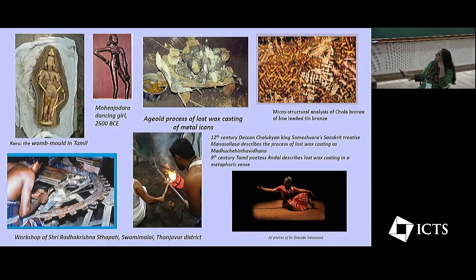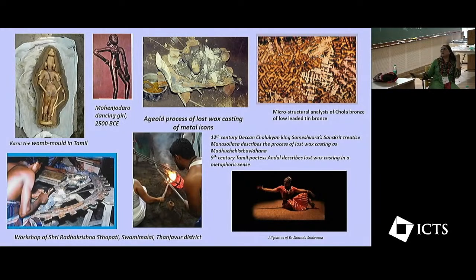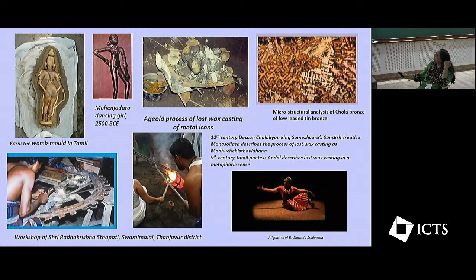And typically in the lost wax casting, what is done is first a wax model is carved of the icon to be made. And here you see from the rear this wax model having been carved. And then it is invested with numerous layers of clay, going from the finest grade of clay to the coarsest layer of clay. And here, what is important is a lot of these bronzes were made on the banks of the Kaveri River. This is Swamimalai, which is just near the Kaveri. So it's really the alluvial clays of the Kaveri which are used to make the mold.